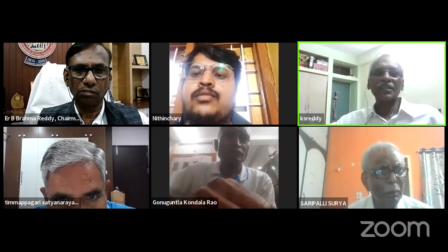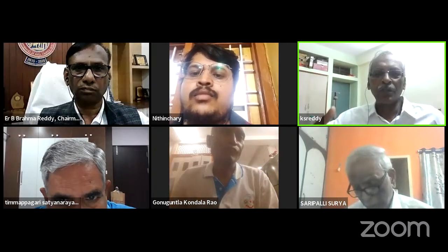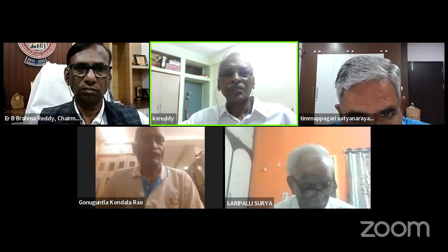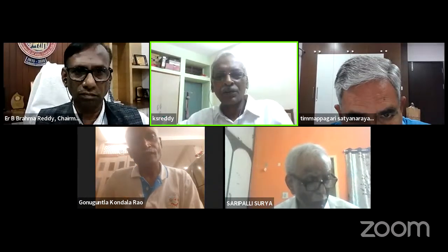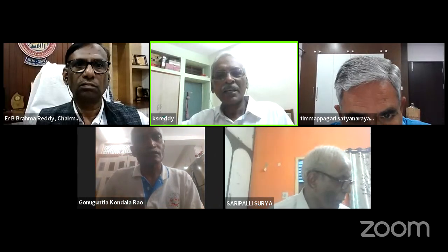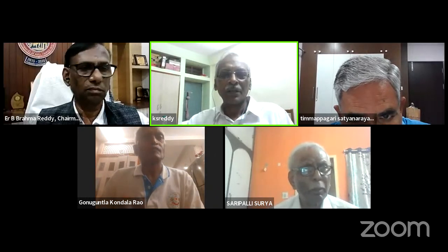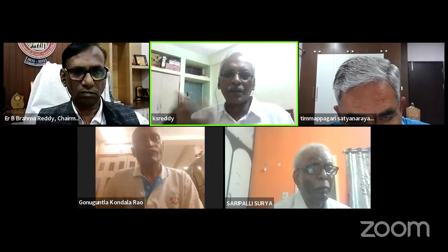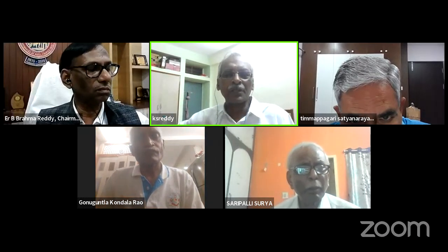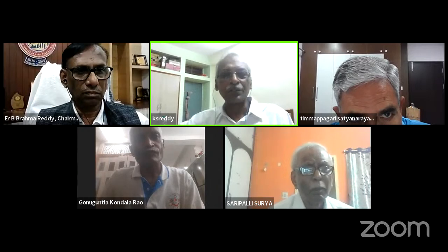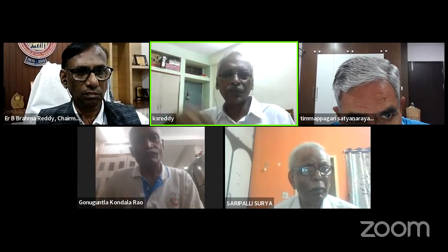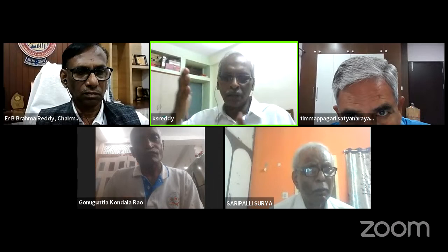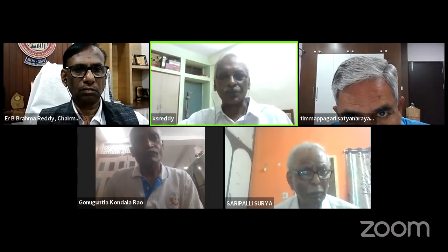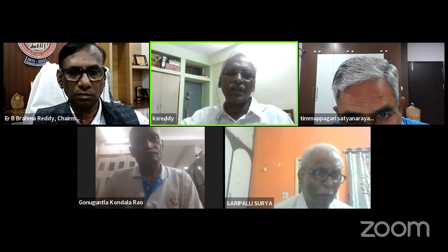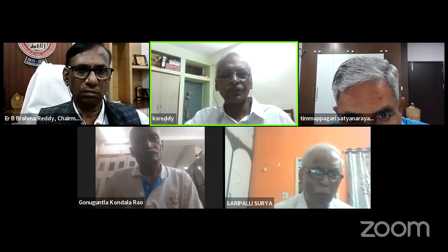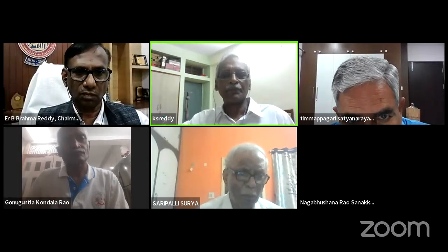You can also do it for DLCs, because sometimes when it's too good a DLC, you are going to have cracks which are too wide. They can actually reflect into the concrete. So there are agencies or organizations that recommend you also cut grooves in DLC, and match your concrete slab joints with those of the DLC grooves. That would prevent the random cracks which generate in DLC from propagating to the concrete slab.